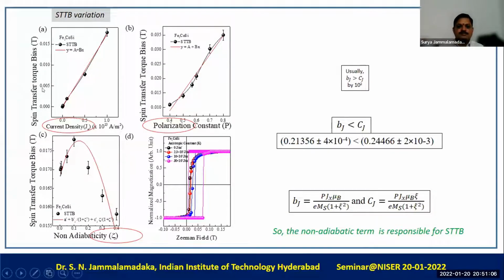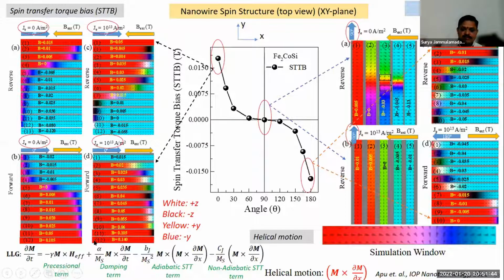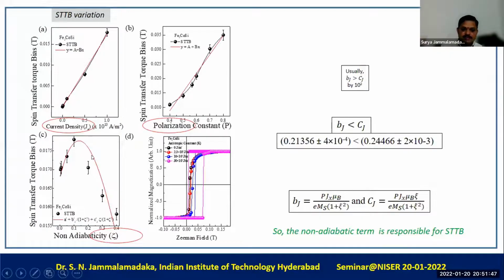So to understand more about this spin transfer torque bias phenomena, we also tried to vary the current density and calculated the spin transfer torque bias. We do see a linear variation for the spin transfer torque bias. And even with the polarization constant, as you increase the polarization constant, we do see an increase in the spin transfer torque bias. Also, we varied the non-adiabaticity, zeta term, and we do see this kind of variation. We fitted this non-adiabaticity term with this expression. Okay. So this is the expression which is mentioned here, from the Landau-Lifshitz-Gilbert equation. We fitted this variation with the Landau-Lifshitz-Gilbert equation. What we could see, we extracted parameters of BJ and CJ from this fitting. So the values that we have obtained are depicted over here.